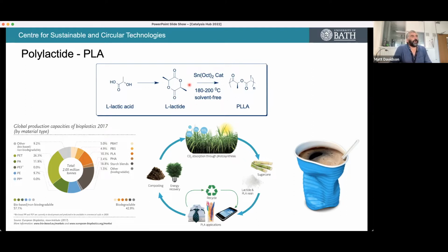The industrial process to do a ring opening polymerization of L-lactide to give high molecular weight and well-controlled poly-L lactide, that's isotactic PLA, is using a tin octanoate catalyst, or at least a tin-based catalyst, typically tin octanoate. And it's done solvent-free, 180 to 200 degrees. It's a melt polymerization, and it gives this nice pure poly-L lactide with appropriate properties.